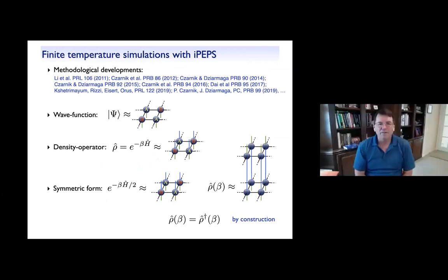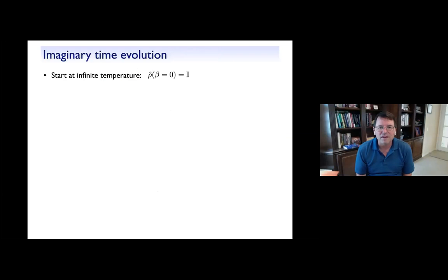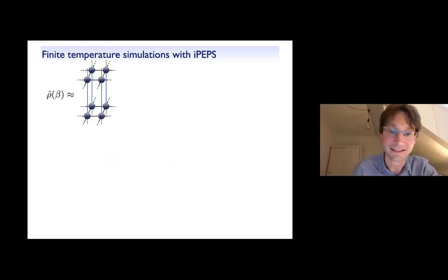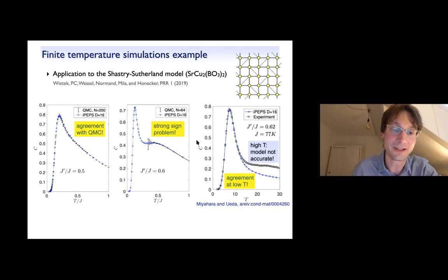I see. So I was sort of surprised that you didn't seem to have trouble going to low temperatures. Were there any tricks? Well, to be fair, the Shastry-Sutherland model is, in that respect, a nice model because it's highly non-trivial from the quantum Monte Carlo point of view, but the ground state itself is a product state in the dimer phase. So the low T behavior here is actually not difficult to obtain, but still, this is relevant for experiments, and it has been extremely difficult to get data at these temperatures with quantum Monte Carlo.